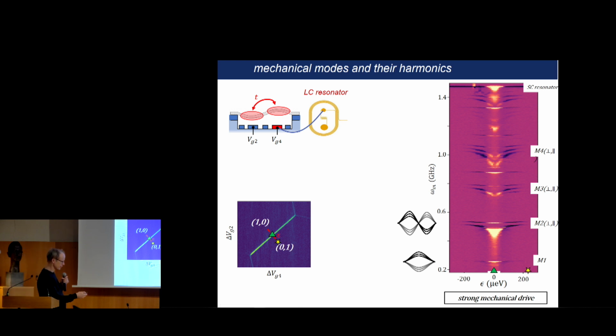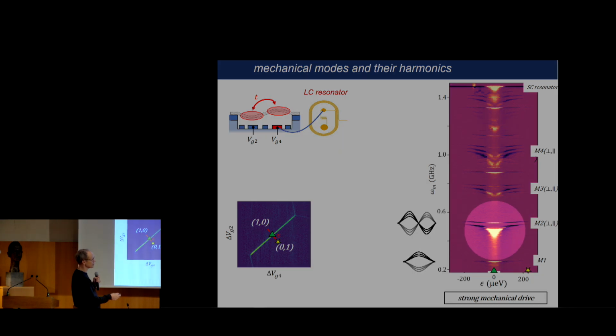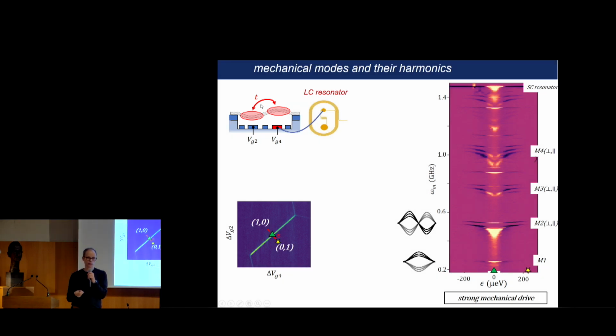And so what is interesting to us is this mode here, because you have one node, and you see that along the nanotube. So it's the mode here. It corresponds to this nanotube that is going up and down. So that's the shape of the eigenmode, and you see that it's very symmetric compared to the double quantum dot, and because of this, you have the strongest coupling strength. Okay, so for this reason, we choose this mechanical mode.